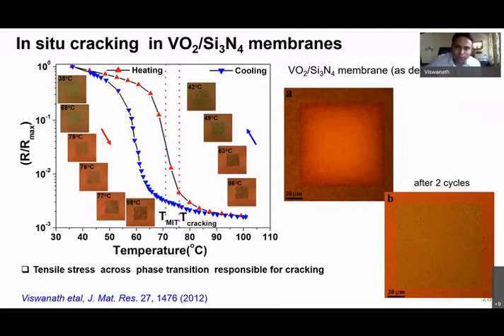Just before that, I want to also show you, even during the phase transformation itself, the fracture is known in single crystals as well as thin membranes. In this case, I have done VO2 coated on a silicon nitride thin membrane. Just during the resistance measurement as a function of temperature, when the transformation is about to get over, I would say slightly above the actual transition temperature,